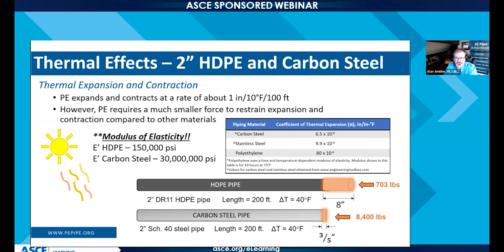Here's some of that theoretical as we follow through more with specific temperature change. One thing that I've observed is that an accurate estimation of what could actually happen in the field, as far as the temperature change that pipe might endure, is pretty much important for what we're looking at. But one of the things that's unique about high density polyethylene is it does have a lower modulus of elasticity than other pipe material types, and a higher coefficient of thermal expansion, which will allow it to change more. So in this example, we simply did 2-inch DR11 HDPE and 2-inch schedule 40 steel, 40-degree temperature change, 200 feet length. The HDPE would move 8 inches.